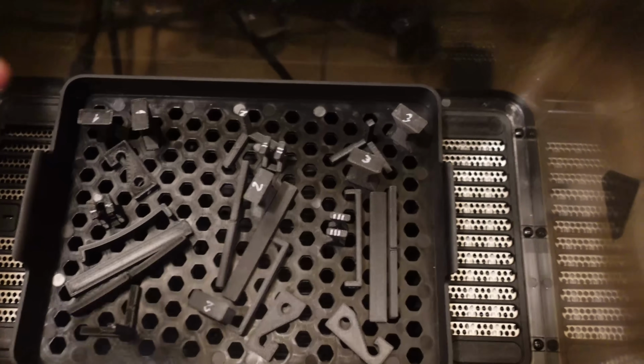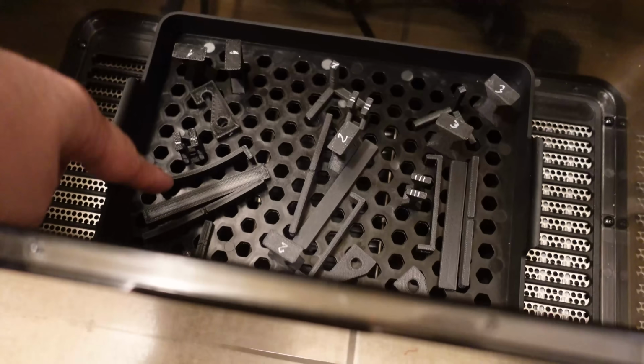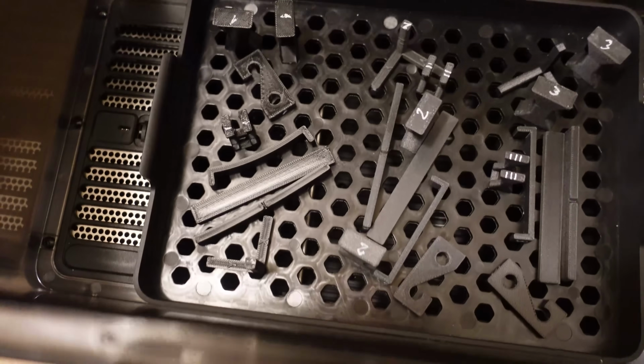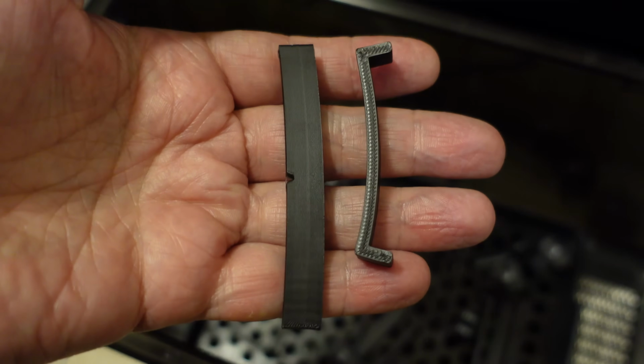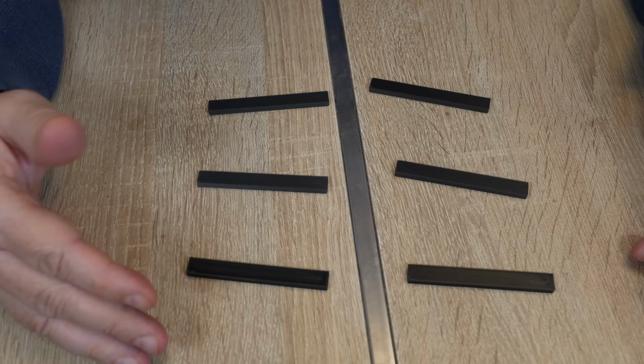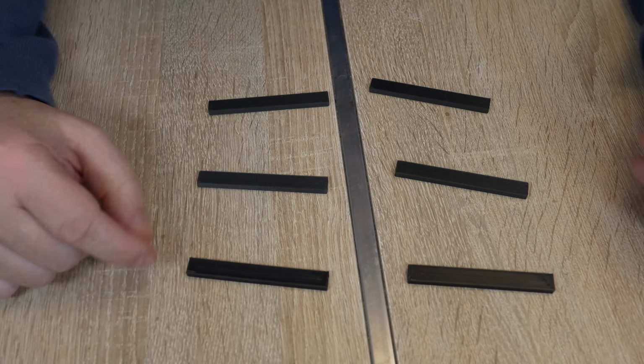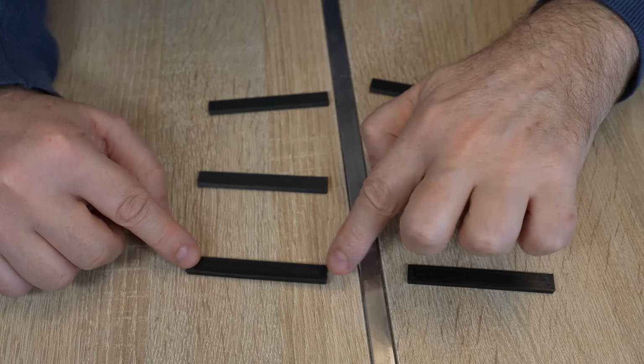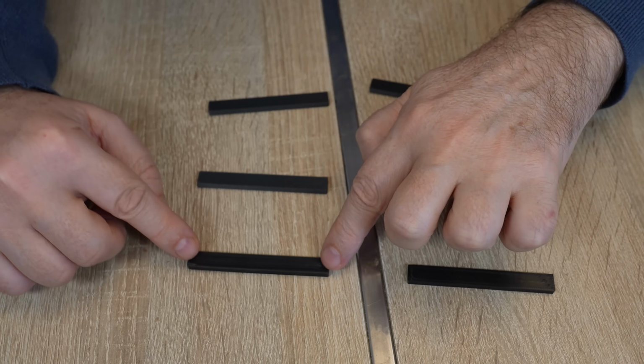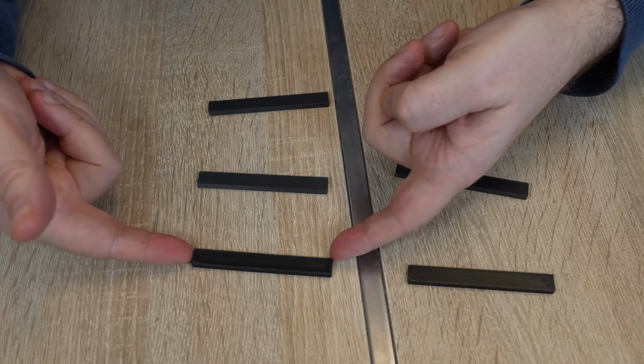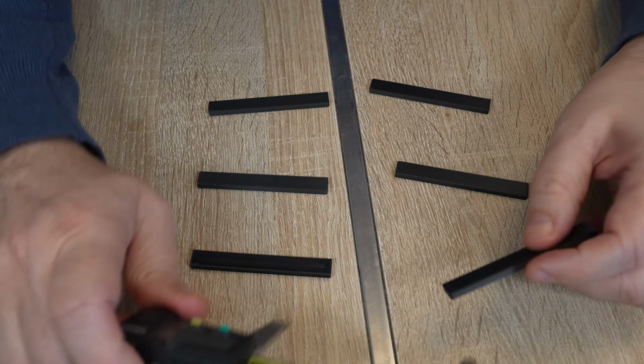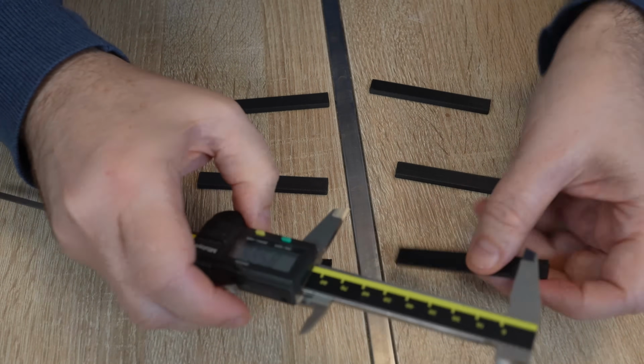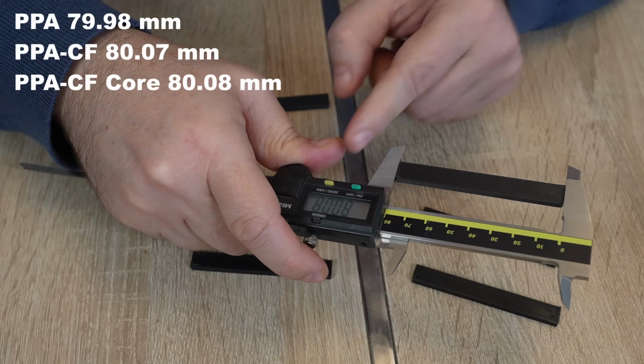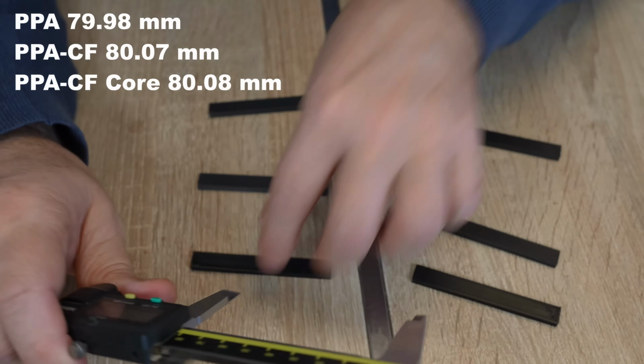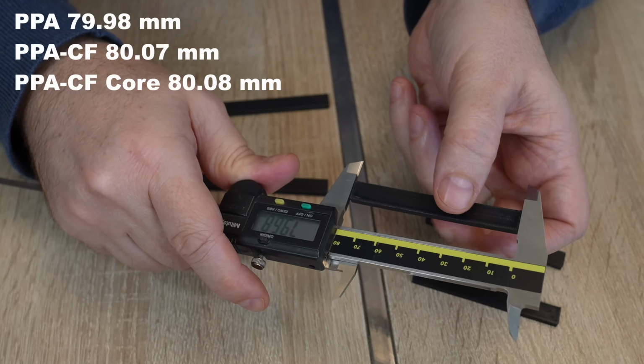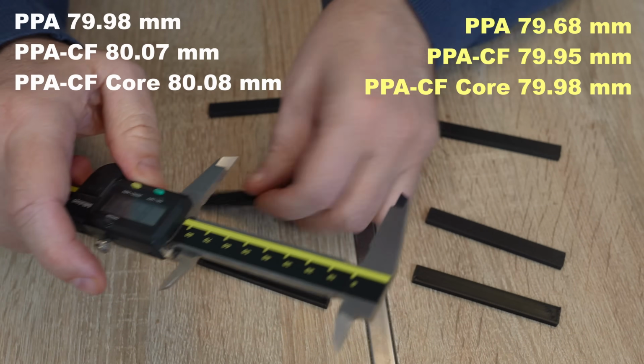At first look, this one looks straight and this one is quite deformed. Yes, so this is why they don't recommend annealing the regular PPA. Let's check the shrinking. These are annealed versions, and I already mentioned that the PPA after annealing had some warping, but I believe that it is measurable. The design length is 80 millimeters, and I'm measuring above the elephant foot. 79.98, 80.07, 80.08, and now annealed versions. 79.68, 79.95, very minimal shrinking.